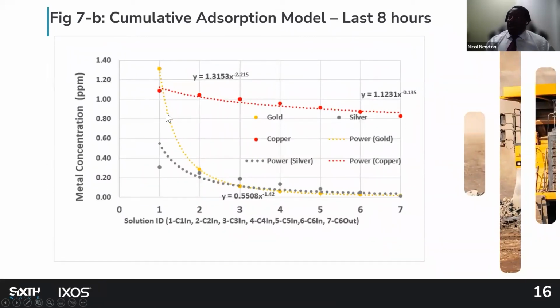We had a similar scenario to what we had for the first 12 hours. But in this case, the copper was already high in the feed solution, yet we still had very little copper getting absorbed on the beads, which was a very good indication. And to a large extent, this did not affect our gold absorption on the beads, which also showed excellent recoveries even in the last tank 6. Same applied with the silver.